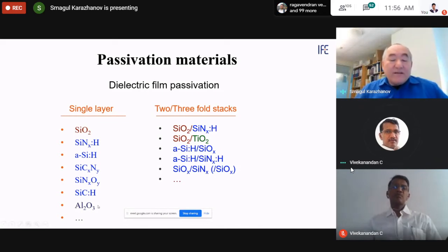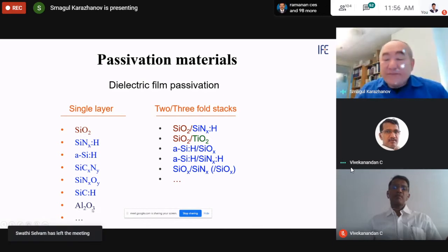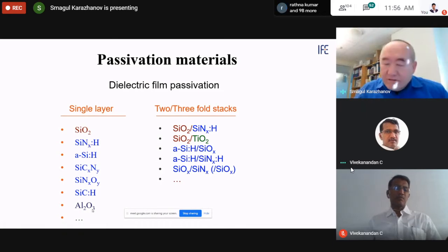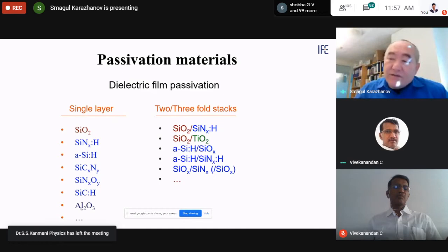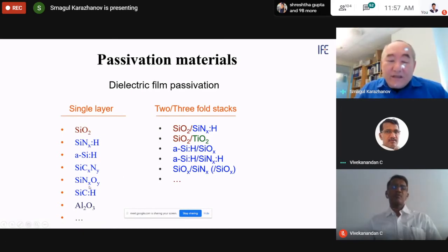There is aluminum oxide. Distinct from silicon nitride, it passivates both N-type and P-type silicon. The only point is that passivation quality is very good if deposition is done by sputtering. But if it's done by PECVD, which is compatible with the silicon solar cell fabrication process, then it's not good enough. So with each of the materials, there are certain problems with passivating.